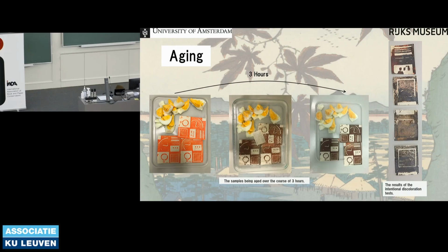I also attempted intentional patination, following the method proposed by Finlayson et al., where she essentially suggested that if you printed acetic acid over the prints prior to exposing them to a source of hydrogen sulfide, it would create a more even and silvery discoloration, and this was hugely successful. The acetic acid prints were much more silvery and had a much more even discoloration than those only exposed to the eggs.